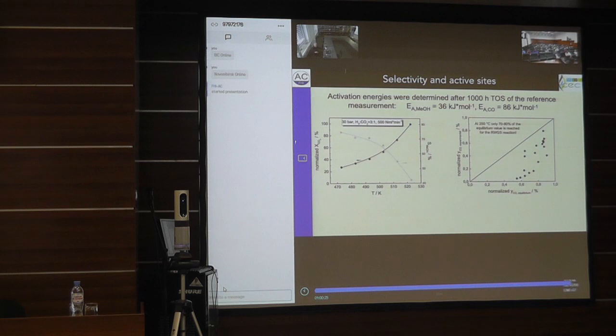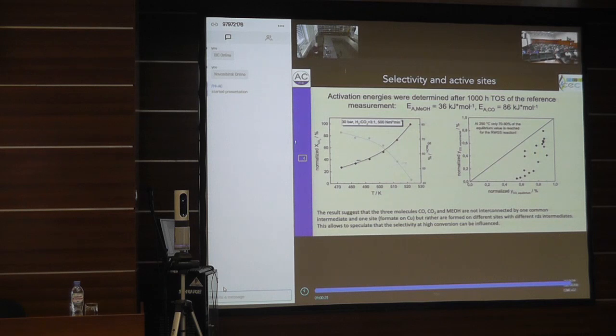And then, of course, the consequence of that is this allows us to speculate that there might be catalysts in the world that have the possibility that for kinetic reasons we can reach one equilibrium under the same conditions faster than the other equilibrium. If that would be the case, that would be a perfect catalyst, and we would love to find it. And that is, of course, one of the key issues: future research in methanol synthesis would have to concentrate on this part.